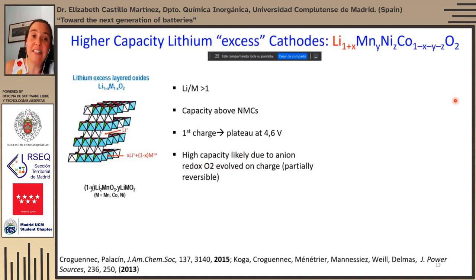Another strategy that is being investigated is the use of lithium-excess layered materials. These materials, and actually what I'm going to be talking about from this point, are materials which are not in commercial batteries yet. The materials I talked about before are the materials that make it into batteries for the time being. But these materials have a lithium to transition metal ratio which is larger than 1. This means that in one interlayer between oxygen lattices, you have only lithium, but in the other layer, you have a mixture of lithium and manganese.